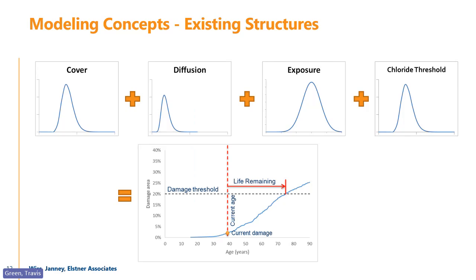And so what we do is we say, listen, we're going to go get a bunch of cover information. We're going to do testing to get the diffusion coefficients of the concrete, right? And these basically result in some kind of distribution curve. We get exposure information, how much chlorides are available, basically, right? What is the surface chloride that we have? And then there's several different chloride thresholds depending on bars. For example, stainless bars have a very high corrosion threshold, right? Black bars have a much lower corrosion threshold. We get all that information, right?